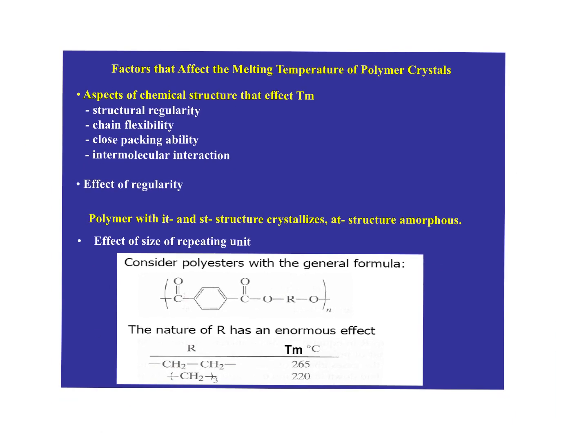Factors that affect the melting point of these polymer crystals. Again, regularity, flexibility, close packing ability, maybe more here than glass transition, and intermolecular interactions. All these things, again, relate to how easily we can extract those chains from the polymer crystal. And if we look at this particular structure, which is basically PET, but we have the ability to vary what R is. Polyethylene terephthalate, melting point of 265. Polypropylene terephthalate, melting point of 220.